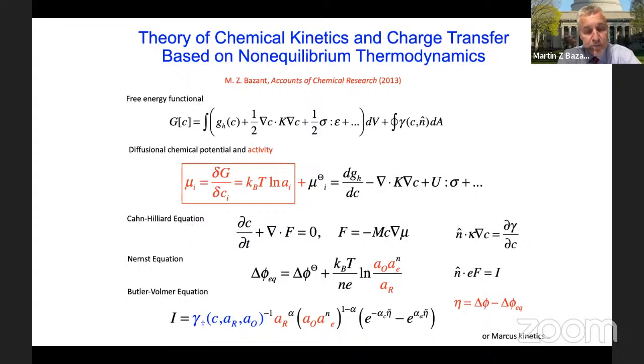in the 1950s. Again, coming back to what's new here, you can formulate, and I did formulate, a variety of somewhat familiar equations from electrochemistry, such as the Nernst equation shown here, giving the equilibrium voltage across an interface, or the Butler-Volmer equation for reaction kinetics, in a consistent way where the activities of the oxidized and reduced species and the electrons naturally come in. And so basically these variational derivatives appear everywhere in the model. They appear in the equilibrium potentials, the reaction rates, and the transport.